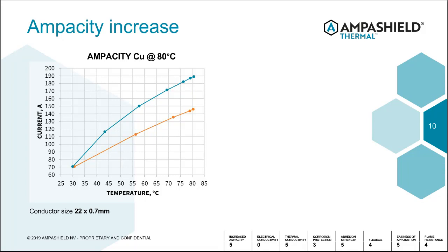a chart representing a copper conductor. 22 by 0.7 is the size. It's a very small copper strip. We see the orange line and we see the blue line. Okay, so this is the ampacity of copper at 80 degrees C. Okay, and we see an increase in ampacity of 32%. So obviously the blue line is representing the copper coated with Ampashield Thermal.